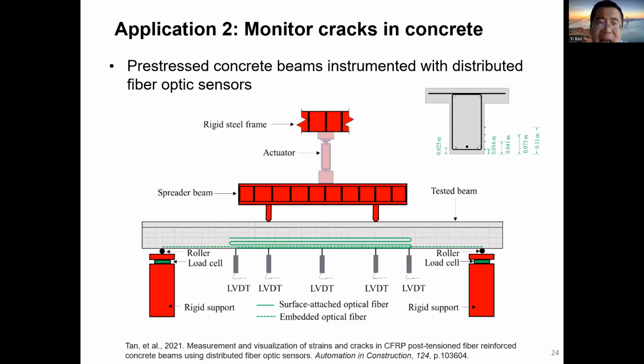And then we extended the application to monitor structures. For example, we have tried to monitor cracks in pre-stressed concrete beams. Pre-stressed concrete is often used in large-scale structures like bridges in order to minimize concrete cracks. In this testing, we deployed a distributed fiber optic sensor both inside of the concrete and also on the surface of concrete. For the inside installation, we did the installation before concrete casting. And then after concrete is hardened, we attached another fiber optic cable on the surface, as shown by the green color curves.